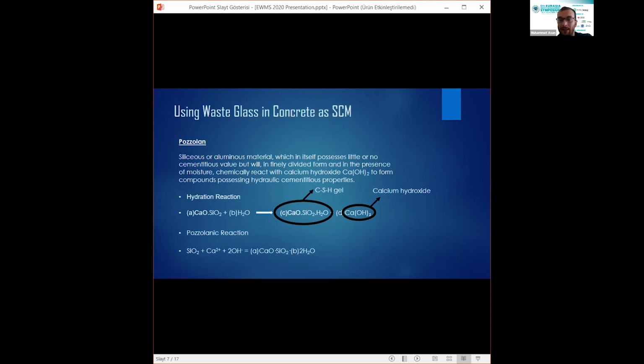Pozzolans are important at this point because the silica in the pozzolans reacts with the slaked lime to form calcium silicate hydrate gel, which provides the development of mechanical and durability properties of concrete. We know that glass has high silica content, so if you use waste glass in powder form, it can cause a pozzolanic reaction in concrete. In some studies, it has been observed that glass has a pozzolanic effect on concrete, but I'm not going to talk about the other research because my time is limited.